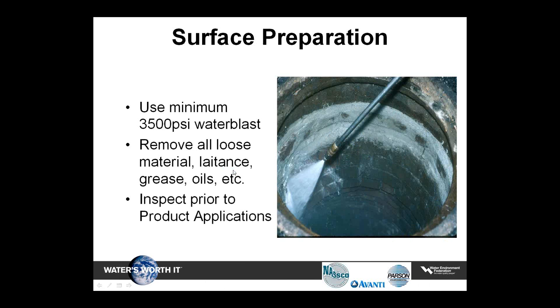Surface preparation. Thorough and proper surface preparation is vital when considering the importance of the adhesion of the cementitious lining to the vertical manhole wall. The lining must be bonded throughout the structure from the underside of the manhole frame to the bench. The surface preparation method of choice is water blasting at around 3,500 psi. This is normally sufficient pressure to remove unwanted dirt and debris from the manhole in order to begin the lining process with a clean, sound surface.